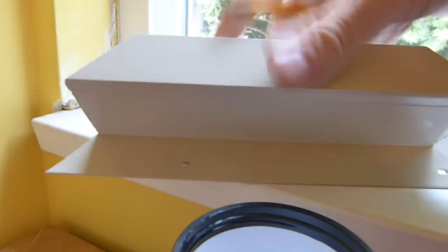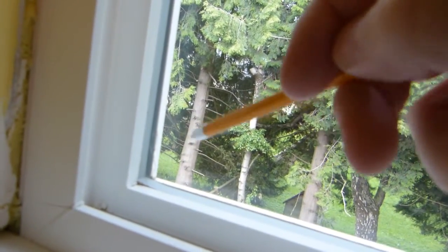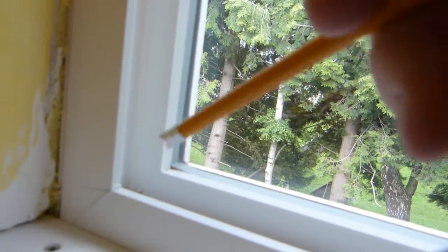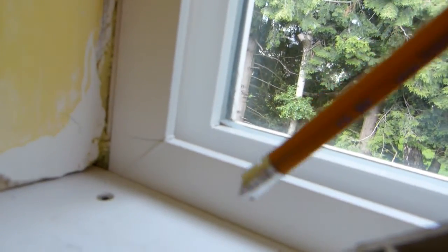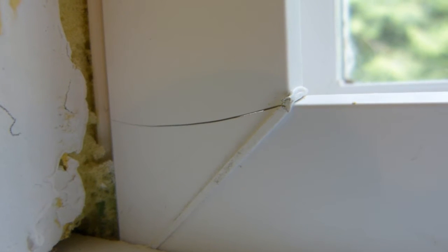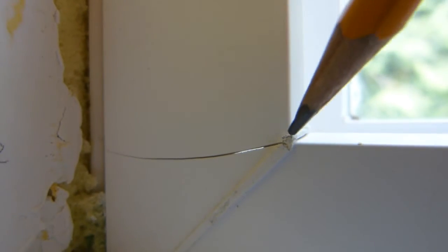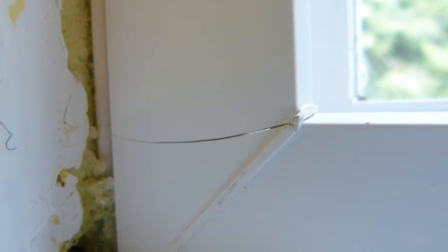The nailing flanges are likely to get damaged, and if the window is rocked too much around corners, then the glass is likely to crack, and other corners are likely to be involved. But it's only one corner, and it's actually just half of one corner. So it's not shipping, it's not installation, it's not delivery, and it's not the expanding foam either. You can see there's a bead of expanding foam behind it, and that didn't crack it either, because the crack is widest here at the plastic weld. So this is a manufacturing mistake.